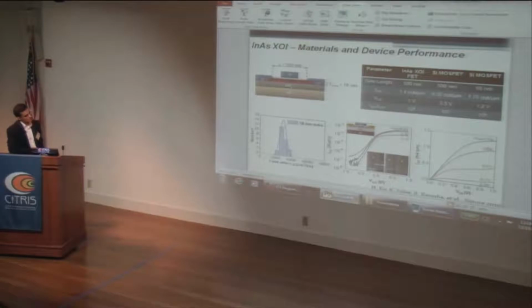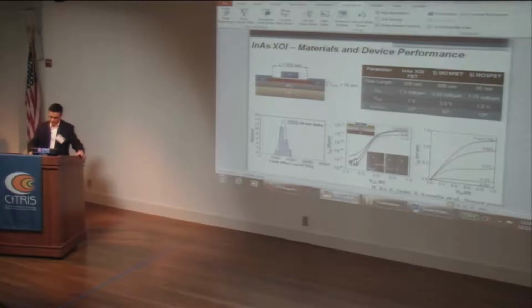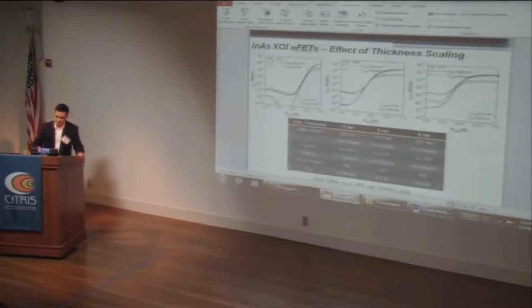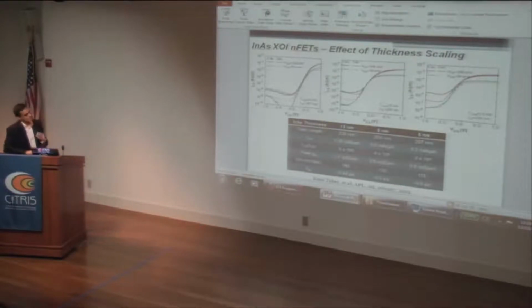But the problem is your subthreshold swing is not very good. Your leakage currents are not very good because we used a body thickness of 18 nanometer. So for the case of silicon, you know that you can make the electrostatics better, you can make the off-state currents better, the leakage currents better by making the body thinner and thinner. And the same is true here. Here I'm showing you the device characteristics for 3 different indium arsenide thicknesses. In this case, it's 13 nanometer, 8 nanometer, and 5 nanometer.